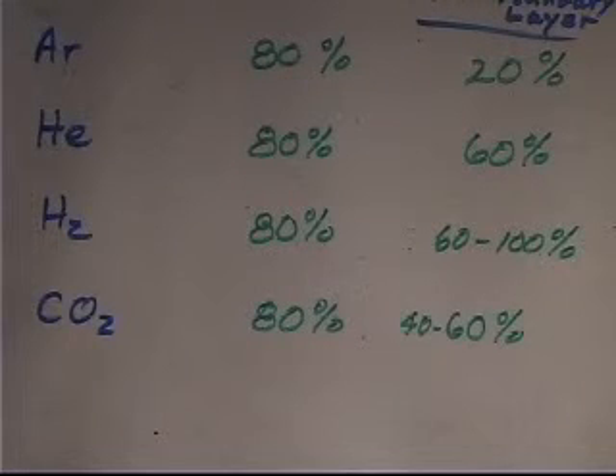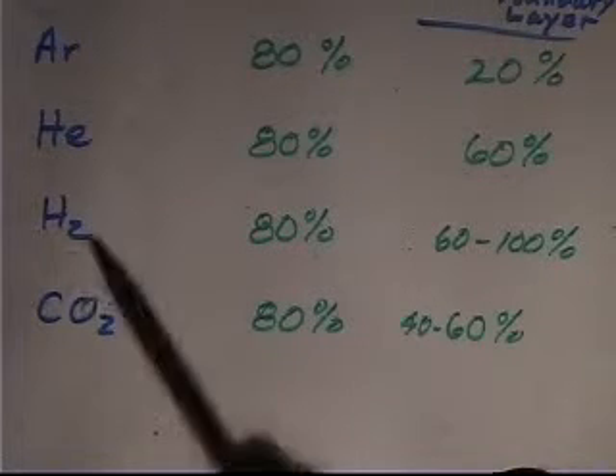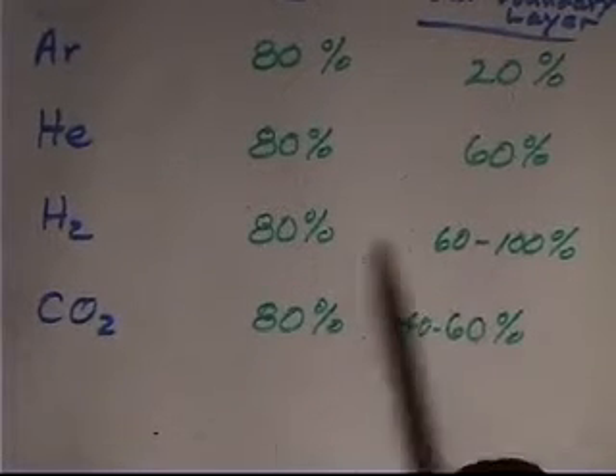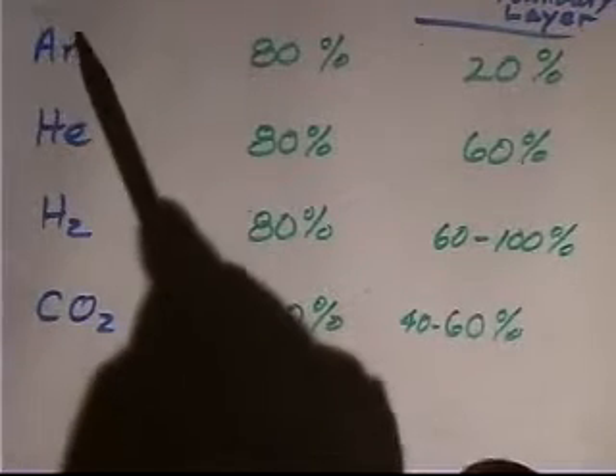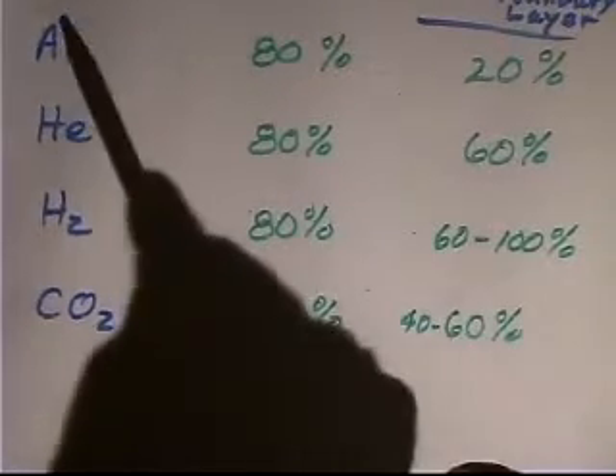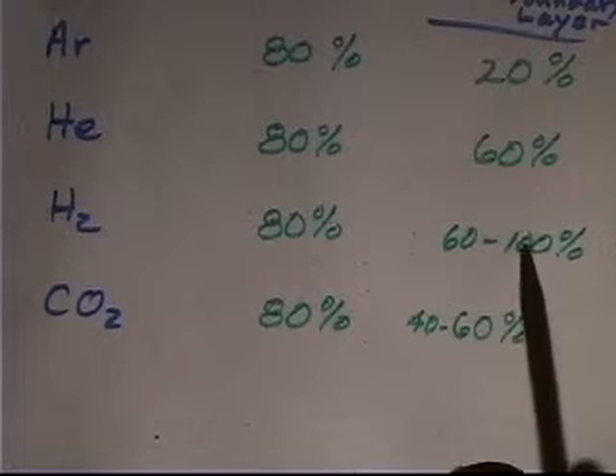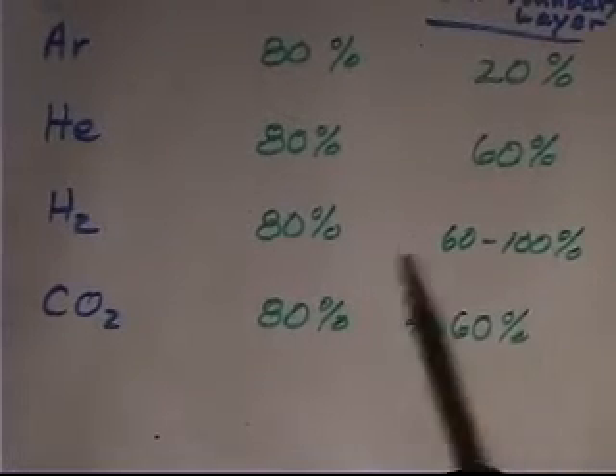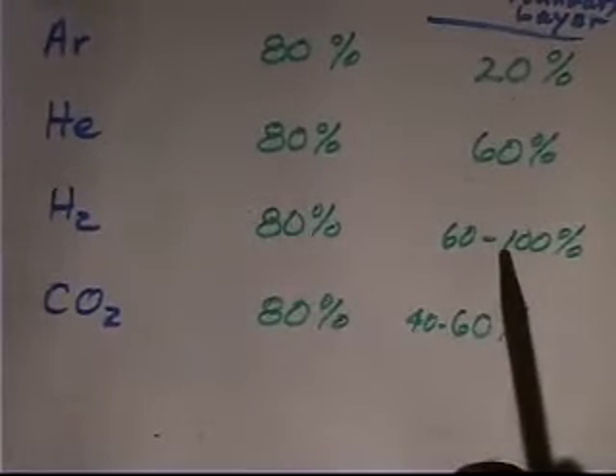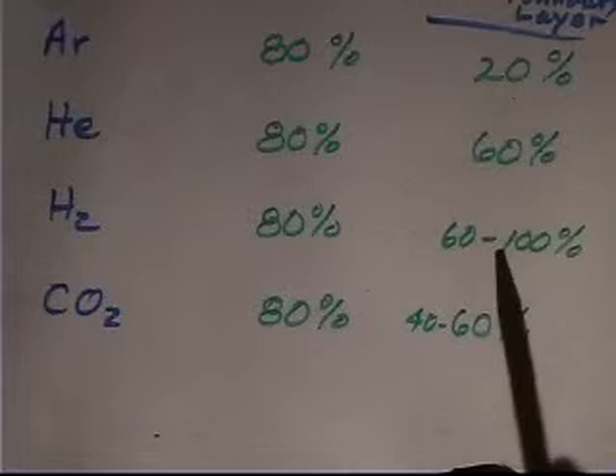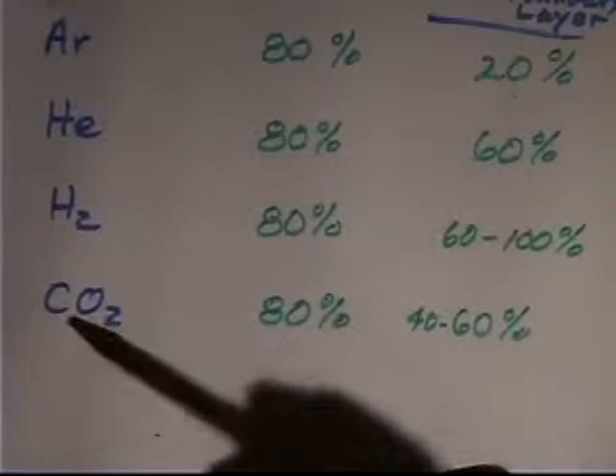Well, turns out that you can't weld carbon steels to get low hydrogen by using argon hydrogen mixtures, but stainless steels, which don't have these hydrogen problems, quite often people use an argon 10% hydrogen or argon 5% hydrogen. And the hydrogen gives much better thermal conductivity, even better than the helium, even with small concentrations, because of the lower molecular weight. But in addition, there's another thing.